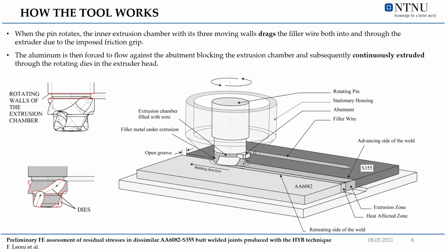As previously said, the HYB process is based on the principle of continuous extrusion and allows joining to be performed using aluminum filler metal additions similar to that done in gas metal arc welding, but without any melting involved. The figure highlights the core parts forming the HYB pinpoint extruder. In the situation of butt welding, the two plates to be joined are divided from each other by a fixed space, so that an I-groove forms between them.